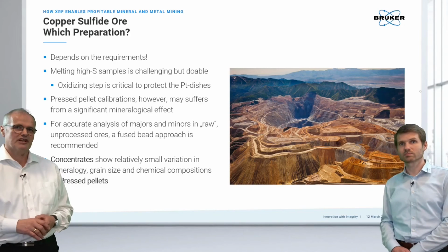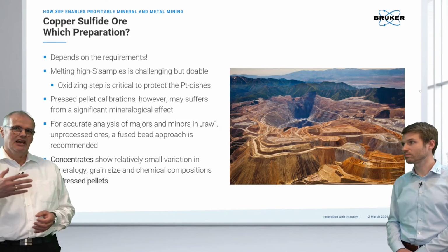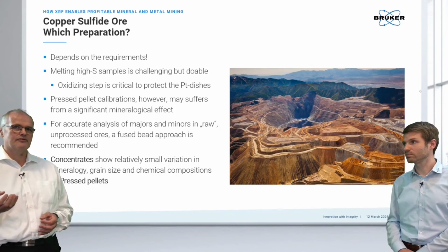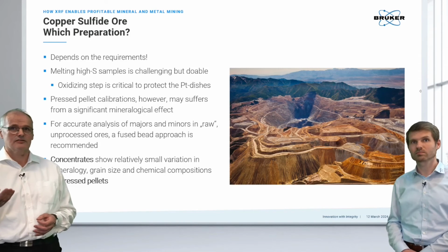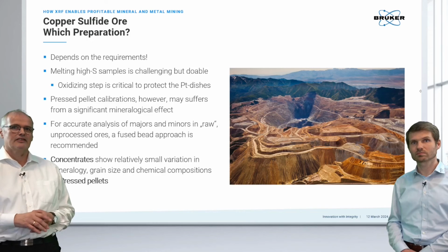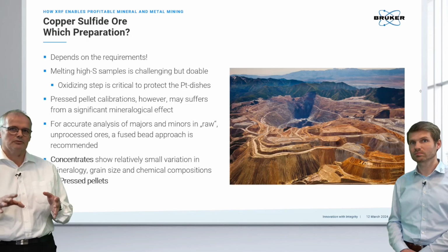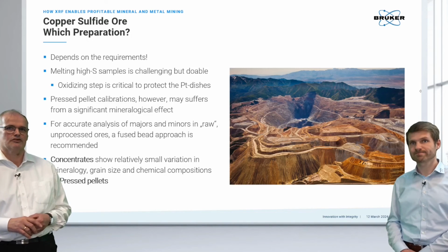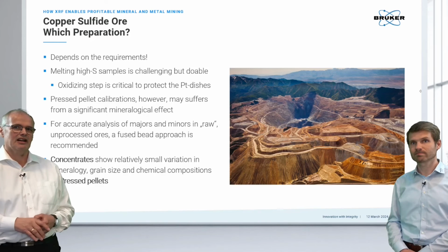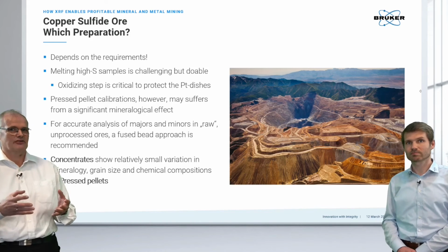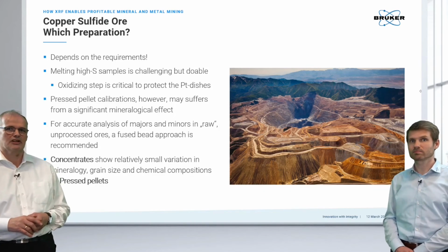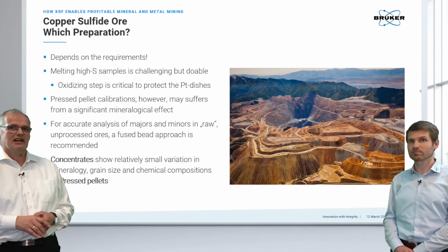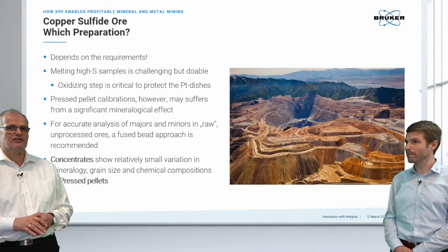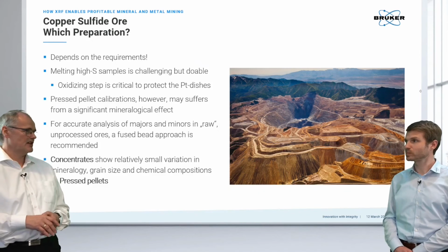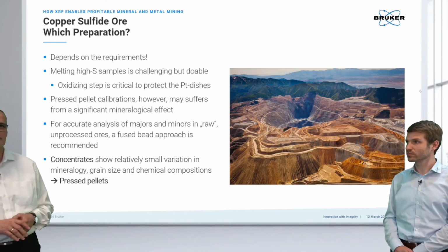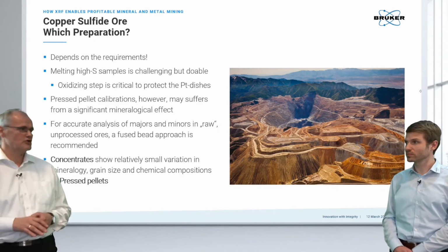The problem with the pressed pellet calibration is that it will suffer because of the sulfur, if this is sulfide or sulfate, this has a huge influence on the mineralogy, but also on the stoichiometry. So for accurate analysis, we really need to have the fused bead approach. The concentrate itself shows pretty low variation, so therefore we can go ahead with pressed pellets, because those are also processed materials with some kind of homogeneous grain size.